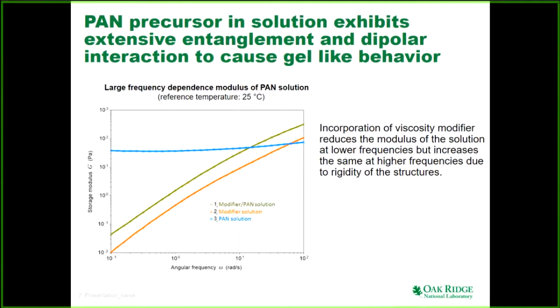On the other hand, look at our modifier solution. It has lower viscosity, as you saw in the previous slide. That means you can increase the throughput. Low viscosity means you can push the material through your spinneret at a higher rate. And not only that, whenever you increase the speed, so you are pulling the fiber at a faster rate, its resistance to flow is increasing. That means the material will not break anymore. Its stiffness is increasing, and as the stiffness is increasing, you can spin the material at a faster rate. So that's exactly what we have accomplished.